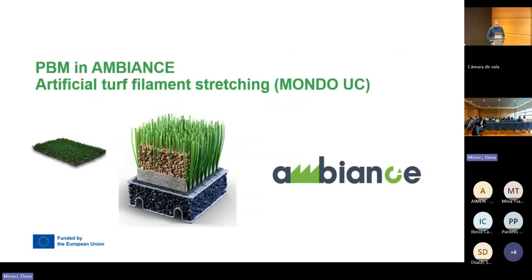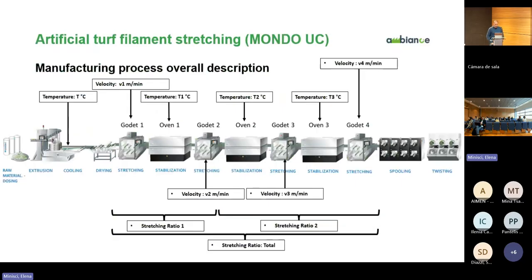So the first use case is the artificial turf filament stretching in the Mondo manufacturing plant. Here we have a scheme of the process. The process starts with the extrusion line, with material coming in in the form of plastic pellets that are extruded, and then cooled. It goes to the stretching part, which is the one we have focused on for this simulation work. It is composed of godets, which are wheels that control velocity and temperature and make the filament pass over different ovens at different temperatures. By controlling the velocities of these godets, we control the stretching imposed on the filament.